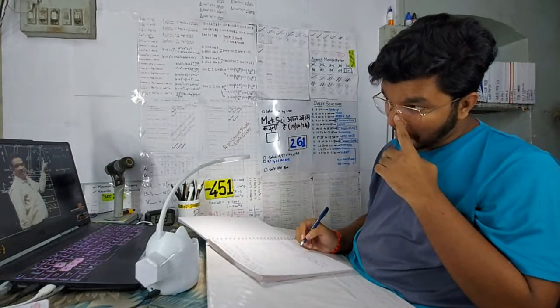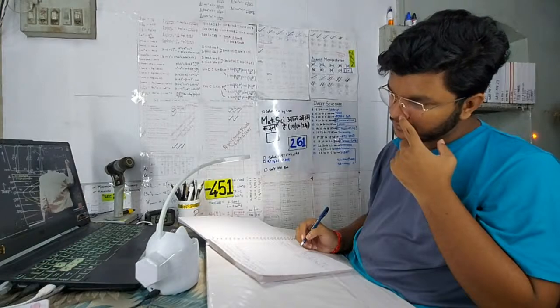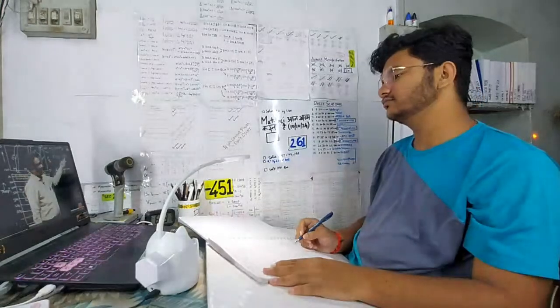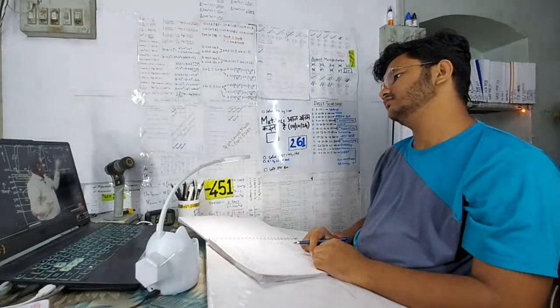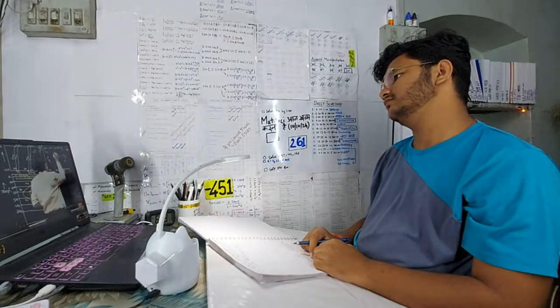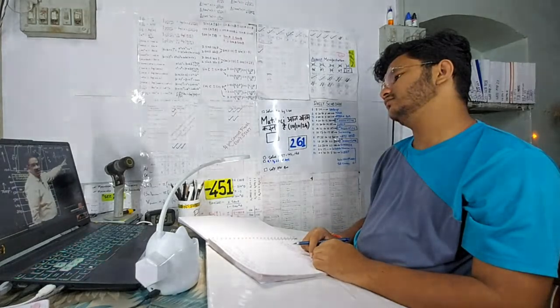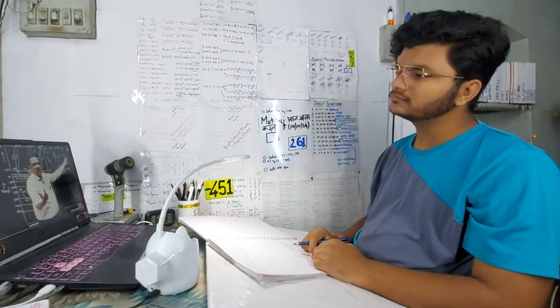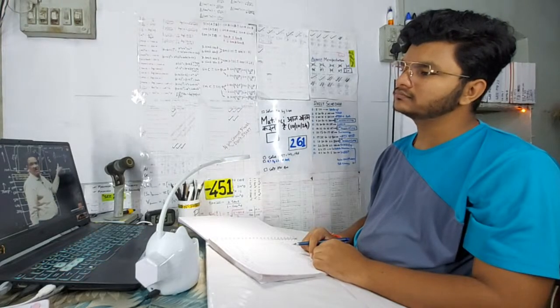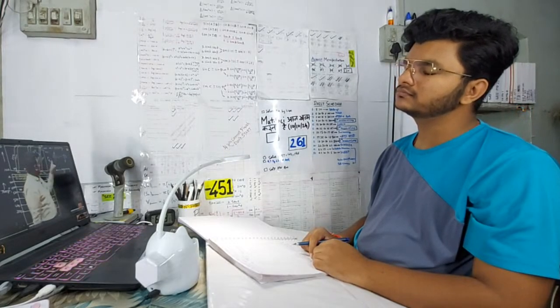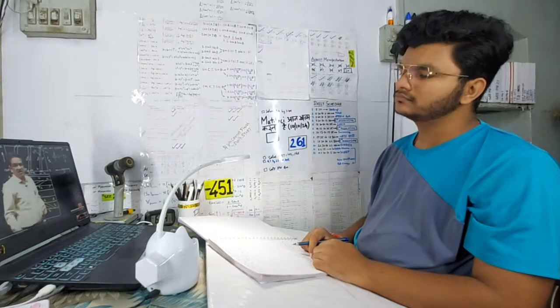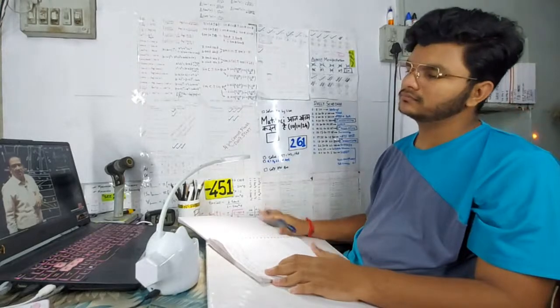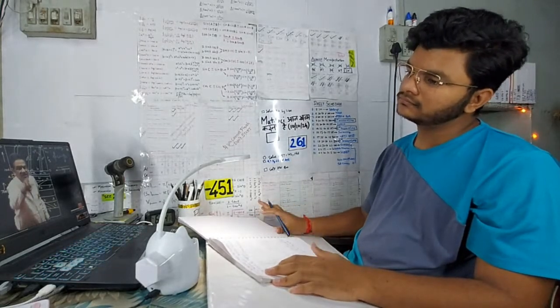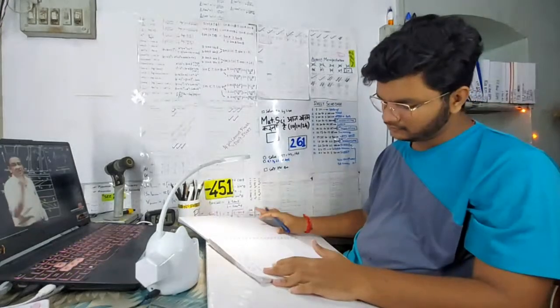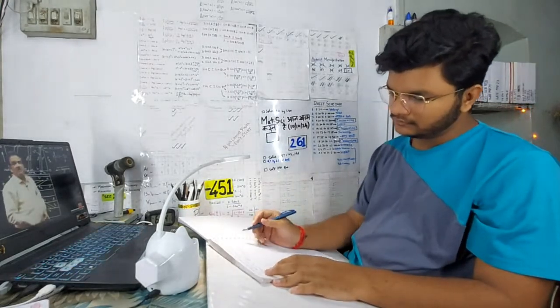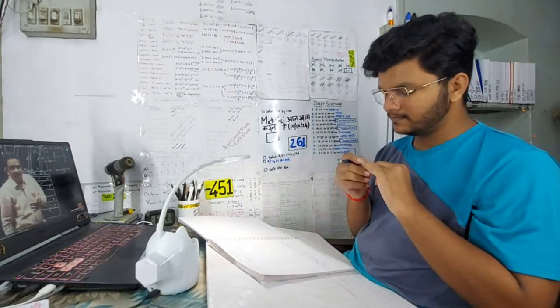See, as temperature is decreased from 300 to 210, this negative quantity becomes smaller, right? Therefore, free energy of the alloy system will increase. When temperature is decreased, T into S will become smaller. Therefore, for a given value of internal energy, the free energy of the alloy system will increase. When the alloy already has a higher level of free energy, will the transformation form immediately or late? It forms immediately, because a higher energy system is more readily available for transformation. That is the reason why Martensite transformation takes place quickly.